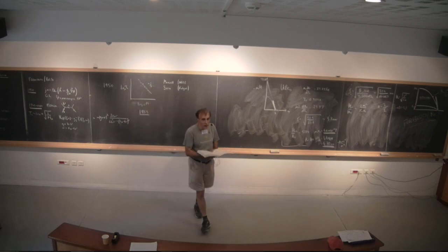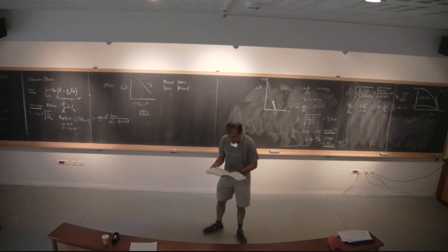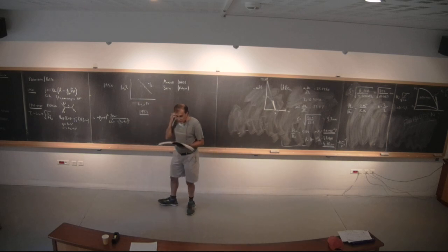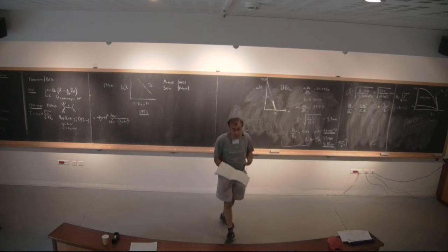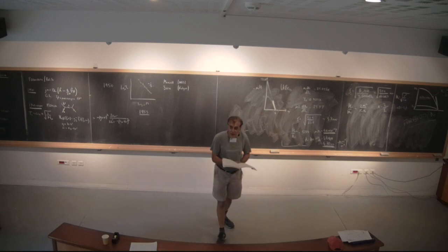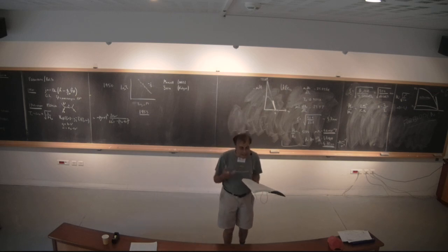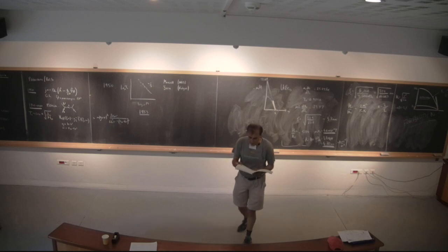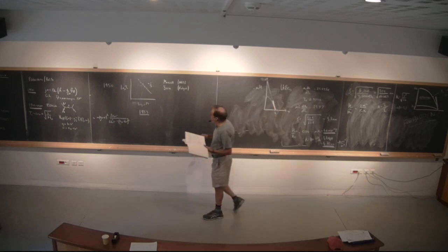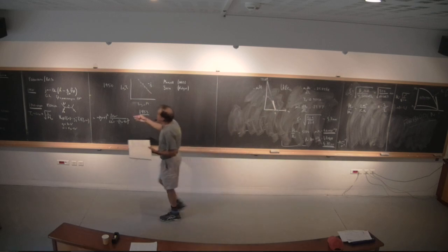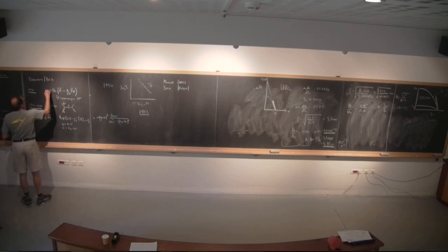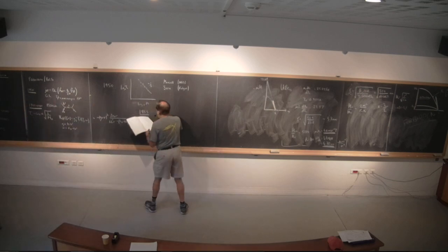And then an outcrop of radar, a young fellow called Brian Pippard, who'd worked on radar during the Second World War, started looking at the effects of microwave radiation on superconductors, and he could measure the skin depth. And he found that somehow the superconductivity didn't switch on right at the surface, but was delayed by some penetration depth, or not penetration depth, coherence length. And he was able to understand his microwave experiments by replacing this local kernel, that J of x is proportional to A of x, by a non-local kernel.